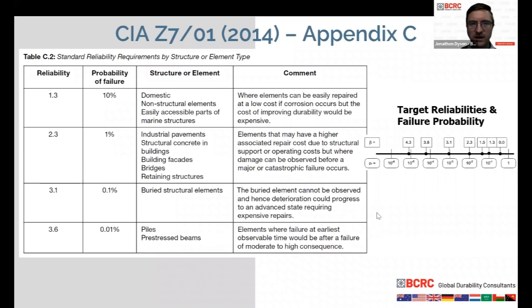So CIA Z701, which is the first volume of the durability series of the recommended practices that Concrete Institute of Australia has published, has a table here which talks about different levels of reliability. So a reliability of 1.3 is a standard, and this is based on international standards as well. Reliability of 1.3 equates to a probability of failure of 10%. Whereas a reliability of 3.6, so a higher reliability, equates to a probability of failure of 0.01%. So you might choose different reliabilities for different types of structures and where the consequences of something occurring may be greater or lower.